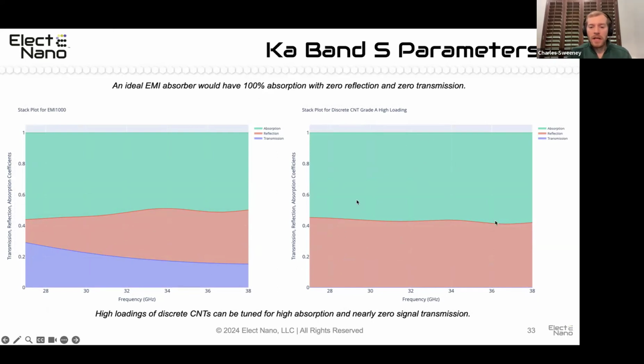And so this is just really cool because it highlights the key benefits of carbon nanotubes to interact with electromagnetic energy at very low loading levels when you have an excellent dispersion and you've achieved percolation in these systems to maximize interactions. So I'll have more updates on that as time goes on, but we're finding a lot of applications where that's useful right now.